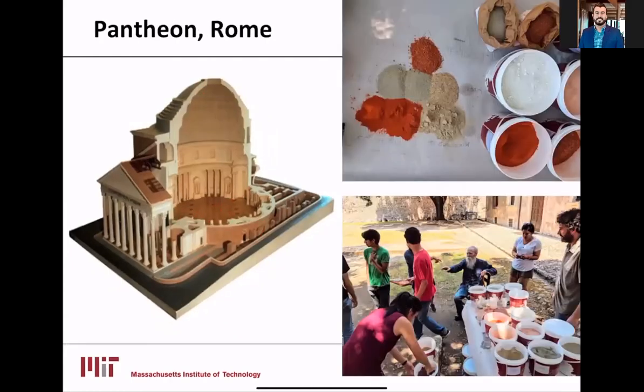We actually have a question related to the stuff on this slide. Leila is asking, what is the value of coccio pesto? Does it replace pozzolan? Yes, the value is fascinating, because it turns out that in a similar way to pozzolans, coccio pesto reacts with lime to produce calcium aluminum silicate hydrates, and that's like an artificial pozzolan that you actually could integrate into your mortar and concrete.